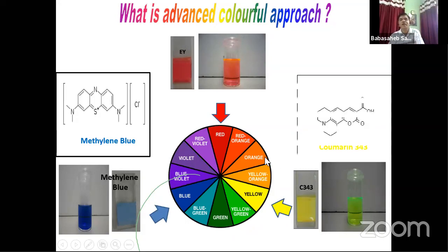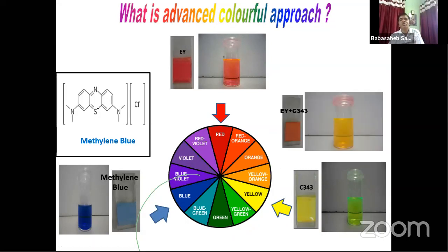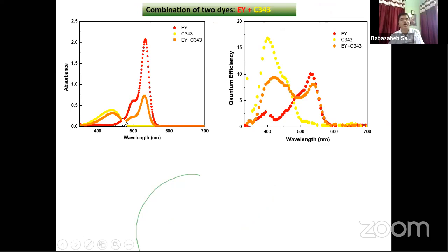And this is the two-dye mix which shows the orange color, adsorbed on the zinc oxide. And the beauty here is that if you mix these two dyes, the yellow dye and the red dye, you can get coverage in the yellow part as well as the red part. This mixed dye is called a cocktail dye, which covers both parts of the solar spectrum, yellow as well as red. And this is just the absorption of the dye. In the next image you can see the quantum efficiency, that is, the incident photon current conversion efficiency: how many electrons are generated per incident photon.